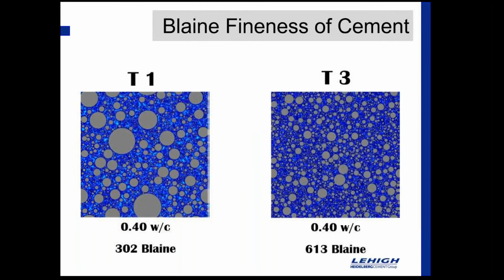If you look at that from a cement model, or actually kind of a paste model standpoint, type 1 would be on the left here at a 0.4 water cement ratio, about 300 Blaine. And you can see there's some porosity involved here. We can see some water, some bigger particles in that computer model. When we jump over to type 3 at the same 0.4 water cement ratio, much denser, much more well compacted. There's not as much porosity through that, and that's a 600 Blaine. So we doubled the Blaine there, and you can see the impact of that type 3 on the actual model performance.